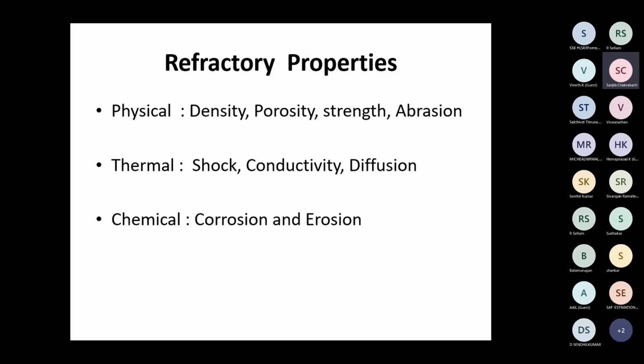Next is refractory properties. What are the refractory properties? The physical properties: density, porosity, strength, and abrasion. A refractory may be either dense or porous. In some places it is used dense. When it is very close to the liquid metal inside the furnace, it has to be dense. It cannot be very porous, otherwise the hot metal will impregnate it. So be very careful about this.